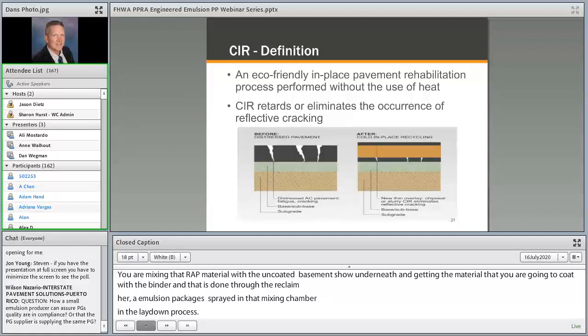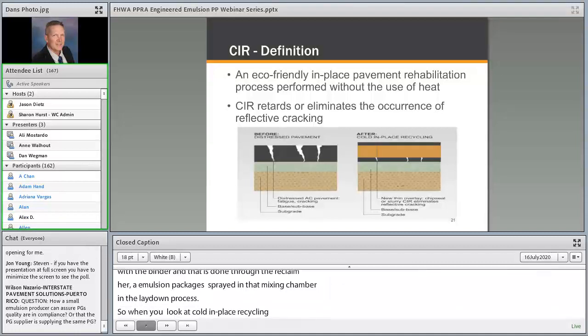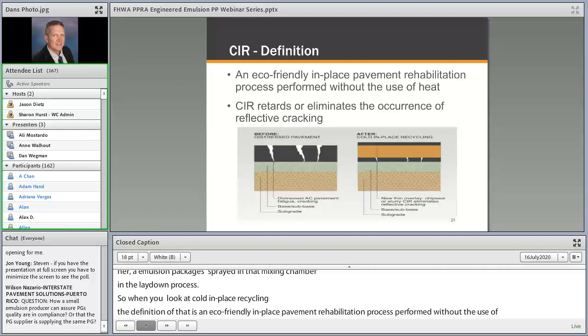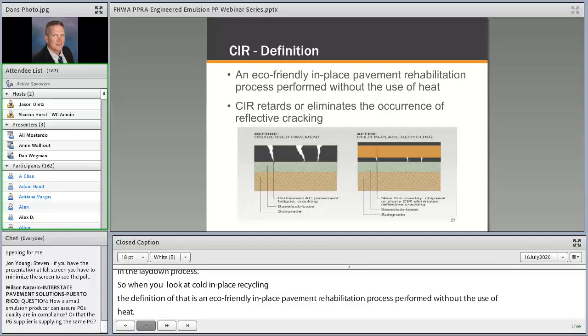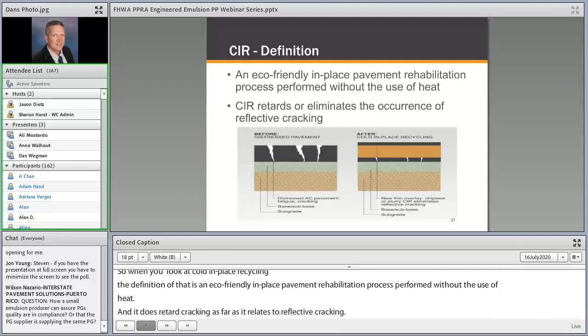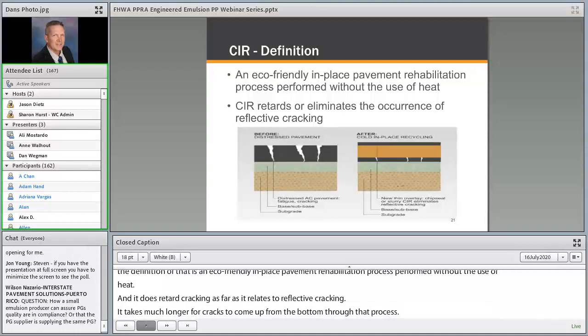So when you look at cold in place recycling, the definition of that is an economic or eco-friendly in place pavement rehabilitation process performed without the use of heat, and it does retard cracking. As far as it relates to reflective cracking, it takes much longer for cracks to come up from the bottom through that process, and that's an aspect we're going to talk about for both CIR and full depth reclamation, is that whole ability to keep cracking from finding a pathway through that stabilized material to the overlying surface material, whether it be pavement or a surface treatment.